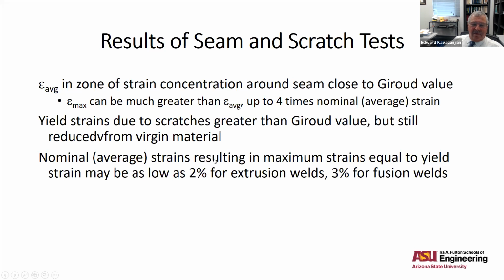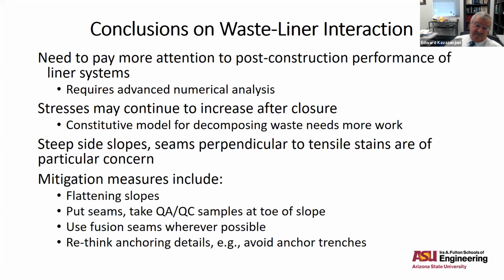And the nominal average strains resulting in maximum strains equal to the yield strain may be as low as 2% for extrusion welds and 3% for fusion welds, which are lower than the 4% value and lower than what we were predicting in some of those analyses of the influence of waste settlement.